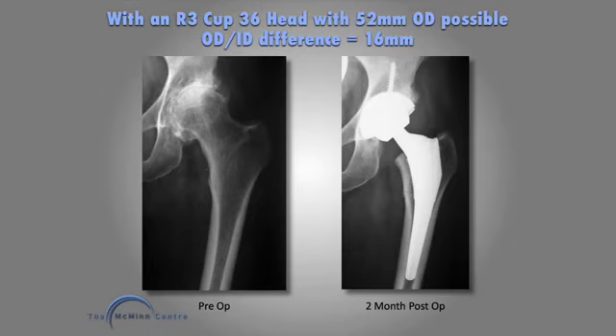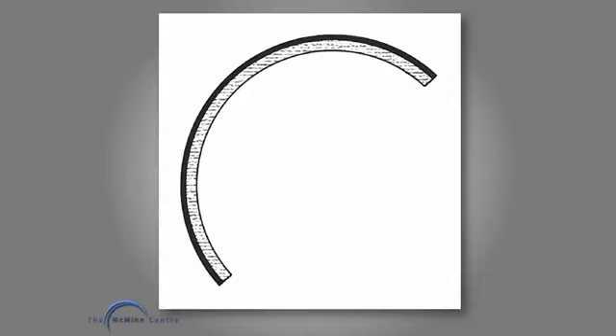And this is because you can put a 3 millimeter thick cup in metal in and be clinically very successful. Try doing that with a shell and a polyethylene liner, and you've got a problem. So that's what you'd end up with if you tried that. You would have a 1 millimeter thick shell and a 2 millimeter thick polyethylene.